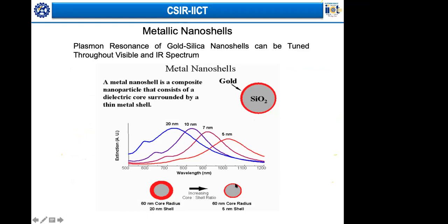As the thickness of the shell is increased, you see that this surface plasmon resonance peak is shifting towards lower wavelengths, and around when it is 20 nanometers, it has come down to between 700 to 750 nanometers. So like that, this shift in the surface plasmon peak gives us an idea about the thickness of the coatings, depending on the material that we have used for coating.